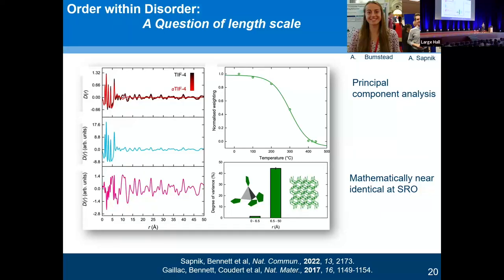And what we find is the weighting at room temperature is mostly this first component, which is mostly the crystalline one. But as we increase the temperature, the weighting of that one goes down, and the weighting of the second component, remember this is a mathematical process, goes up. You can start breaking that down further into different length scales. And what you realize is that on the short range order, nothing really changes. But what is changing is the way in which these building units are interacting with each other. So we get a lot more variance in the higher degrees of ordering, but it does mean that our initial coordination environments are still present.